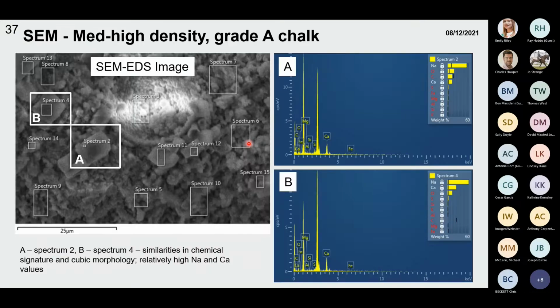When I've come to undertake the EDS analysis on it, I'm getting quite a significant amount of sodium and calcium values in there. Given that the habit of these particular crystals is cubic, and the prevalent element in there is sodium, the likelihood is this is haloclasty weathering within that particular chalk. That, in combination with the location where the material was sampled from, gives an indication as to what we're actually looking at.